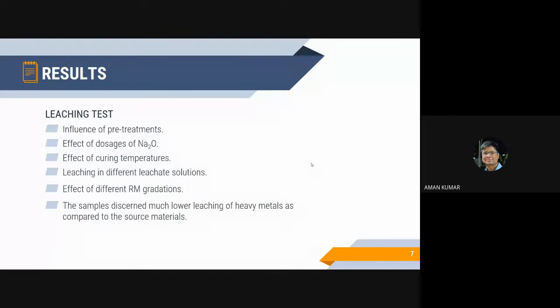Effects of a number of parameters were analyzed, such as the various pre-treatments provided to the geopolymer samples, the effect of dosage of alkali activator, the effect of curing temperature, etc. The studies reported a heavy metal leaching concentration lower than that prescribed by the United States Environmental Protection Agency, that is the US EPA. Moreover, the leaching of heavy metals from the prepared samples was lower than the corresponding source materials. The heavy metals in the geopolymer were in the oxidizable and residual fractions, which were more stable. Hence, the red mud geopolymer mixture was speculated to be a safe alternative to cement composites.